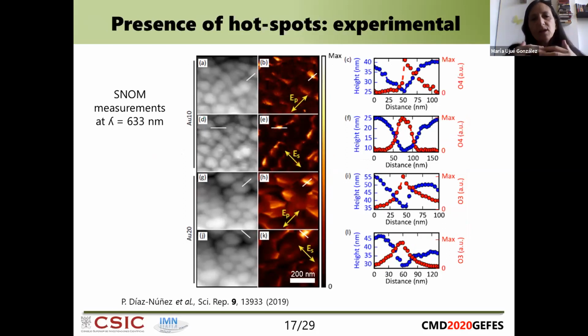And so if you have SERS enhancement, as Isabel just introduced very nicely in the previous talk, what you need is to have some areas where you have a field enhancement, what are also called hotspots. So with scanning near field optical microscopy, by scanning a tip on top of the surfaces, what we did is to try to characterize these hotspots, these points where we had a stronger field.